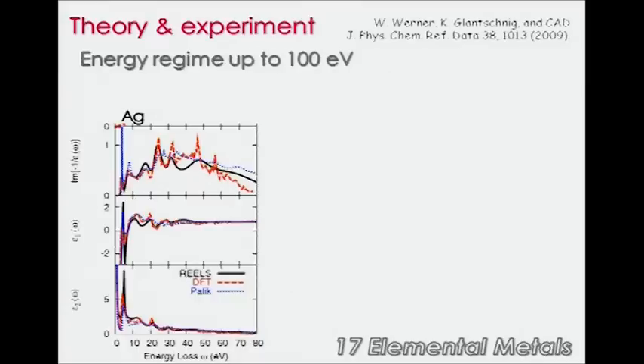And what we will see throughout all these materials is that all the absorption onsets and the structure of the optical spectra agree very well with each other. And they agree much better than with the old Palik data, where you see many discrepancies. So the new data and the DFT data agree very well.